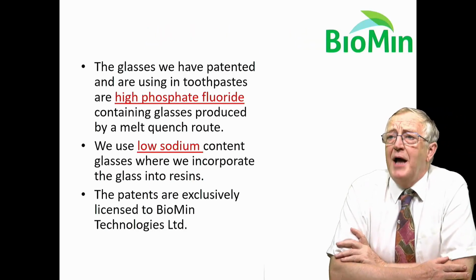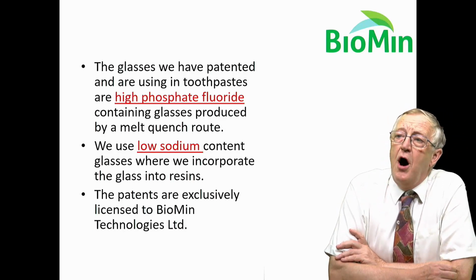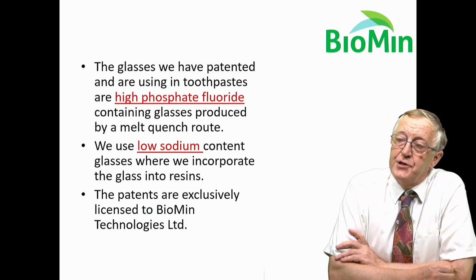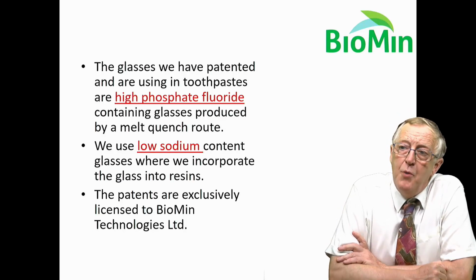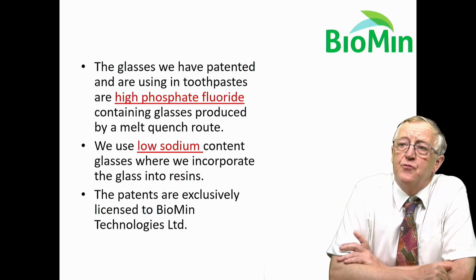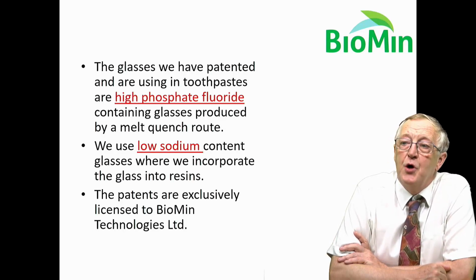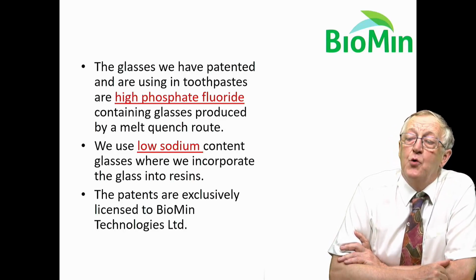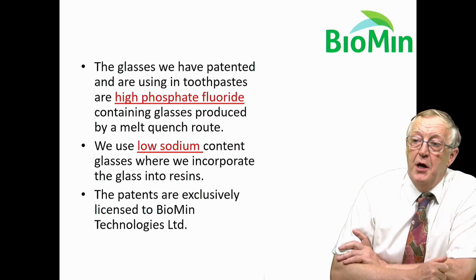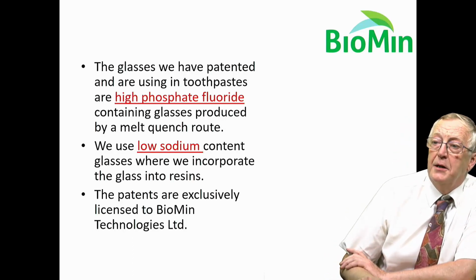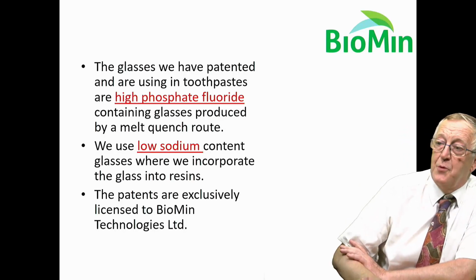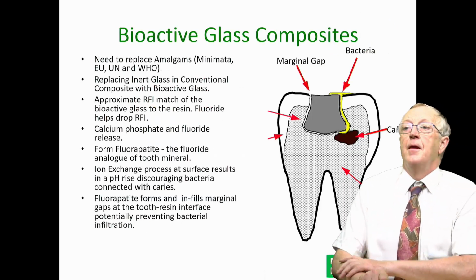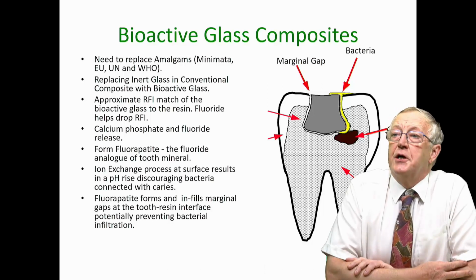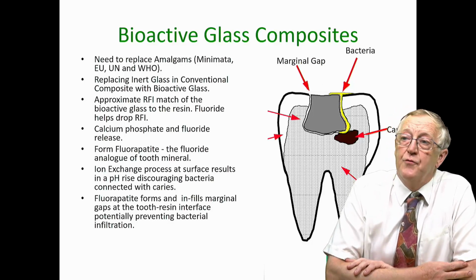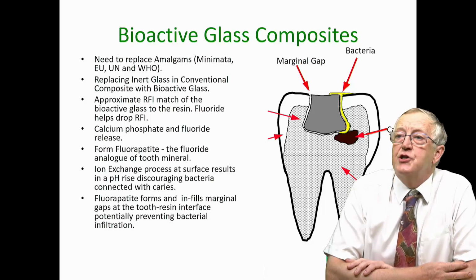The glasses we've patented and are using in toothpastes are high phosphate fluoride containing glasses produced by melt quench route. But when it comes to composites or putting them into resins, we use very low sodium content glasses. And we also use higher fluoride contents. And the patents are being licensed by Biomin Technologies out to other companies. We need to replace mercury-based amalgams because of the reasons I cited earlier in terms of the Minamata and EU and UN legislations and agreements.